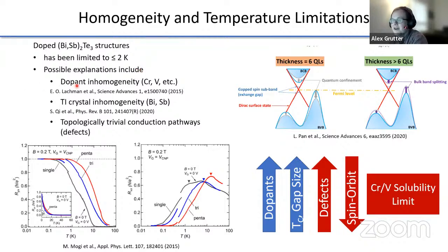And one of them that's very often cited is dopant inhomogeneity. So the idea that, sure, really close to your chromium or your vanadium dopants, the gap induced in the surface state by your magnetic moment is quite large. And this has been demonstrated a number of times. But you have a tendency to have dopant clustering. It's not uniform. Maybe further away from your dopant, you have a much smaller gap. And so since it's not uniform, your overall effective gap in the surface state is relatively small. And so your quantization temperature is also quite small.